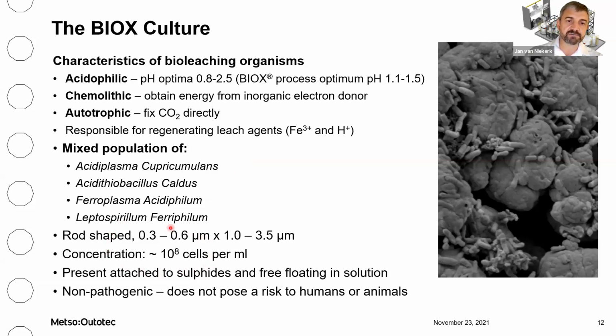Interesting to note the concentration of bacterial cells per milliliter, and for a healthy population, the concentrations will be in the order of 10^8 cells per milliliter. The bacteria are present as both free-floating as well as attached to the sulphides in the slurry. It's important also to note that the bacteria are non-pathogenic, and therefore do not pose a risk to humans or animals. But it must be noted that the slurry itself contains dissolved iron, arsenic, and sulfur at a very low pH, so the slurry itself is toxic for humans.